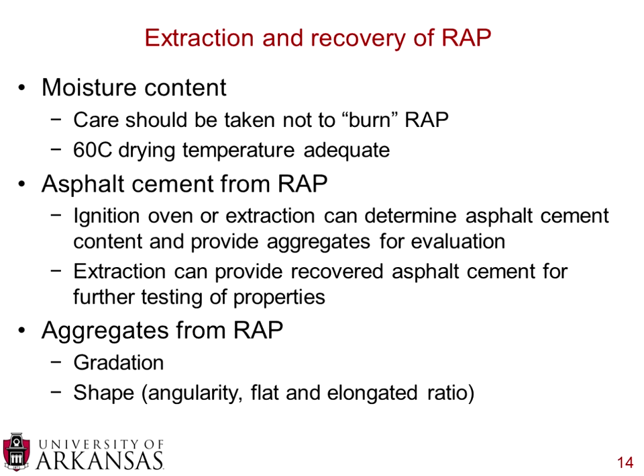Then when you get the asphalt cement from the RAP, you can, as I mentioned, use an ignition oven. And an ignition oven essentially burns all of the asphalt cement off the sample. It gets to very, very high temperatures. Or you can run what's called an extraction. And that's where you use chemicals to pull the asphalt cement off of the aggregate. And you can take that asphalt cement and chemical blend, remove the chemical, and you're left with what's called the extracted asphalt cement. And you can get asphalt cement from that in order to test to understand the properties, and then you can also test the aggregates after that.